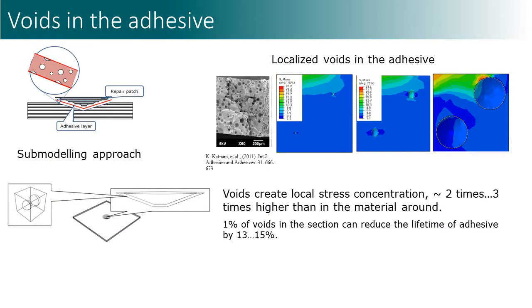A critical factor for the repair quality is the presence of voids in the adhesive layer. We modeled the voids using the submodeling technique. It was observed that voids create local stress concentration in the adhesive, up to 2 times higher than in the material around. If there are voids in a highly stressed region, this will shorten the post-repair lifetime.